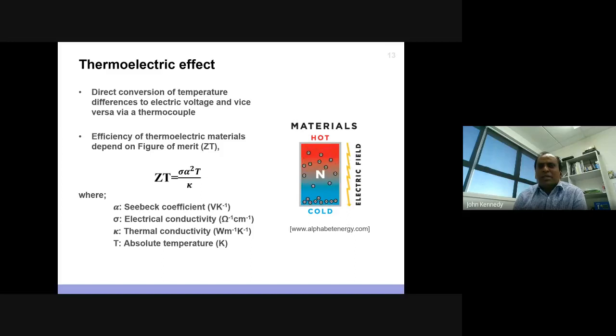What is thermoelectric? As you know, it's a direct conversion of a temperature difference to electrical voltage, and you can go the other way around as well. The efficiency of thermoelectric materials depends on a figure of merit, which is alpha squared sigma T by K, as you know. It's the Seebeck coefficient squared, times electrical conductivity, at a particular temperature, divided by thermal conductivity. It's a simple equation we all studied, and you can imagine the challenges by looking at it.